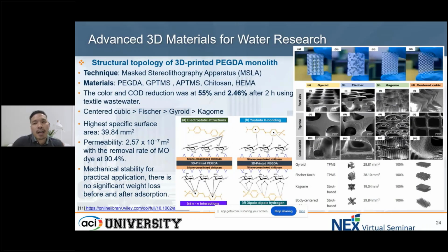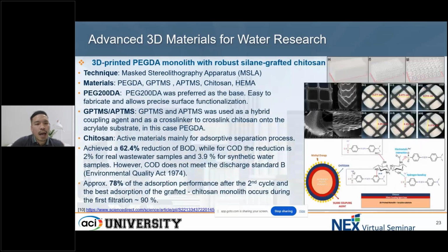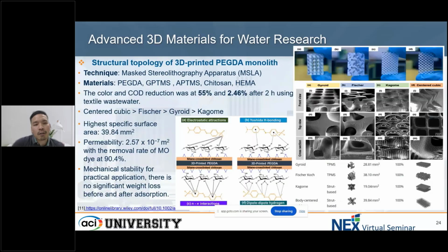We found that the centered cubic structure, which I showed in the previous slide, gives quite a better performance compared to the Fischer, gyroids, and the kagome. Besides that, the cubic gives the highest permeability, with the removal of the MO dye at 90.4%. So this gives a very good mechanical stability for practical application.